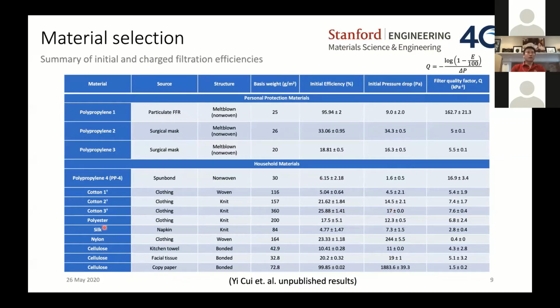Let's look at polyester. Polyester is also widely available. This is the one we are testing. It is a knitting process, 200 GSM, 17% filtration efficiency, 12 Pa pressure drop, quality factor close to 7. Also pretty good materials. Silk, quality factor is lower. It's about 3. And its filtration efficiency is not that high. Air pressure drop, of course, is low, but after you consider both, it is about 3. I think still usable, silk, not as good as cotton or polyester.